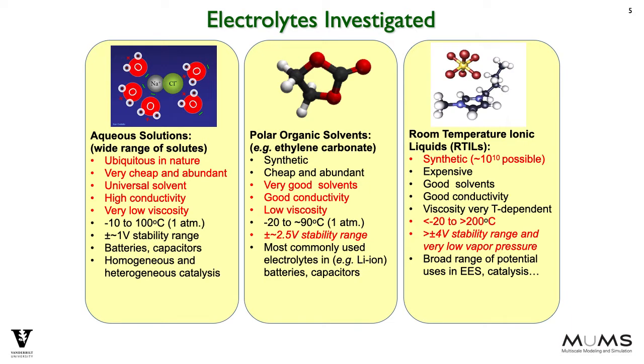The electrolytes we have studied in the FIRST Center include aqueous electrolytes, which have many positive properties, but are limited in electrochemical stability to plus or minus 1 volt due to the water. This leads to replacing water by polar organic solvents, such as ethylene carbonate, which have better electrochemical stability, plus or minus 2.5 volts approximately, but at higher cost. Another approach which has been pursued by many researchers recently is to use neat room temperature ionic liquids so that there is no solvent in the electrolyte. These have high electrochemical stability, approximately plus or minus 4 volts, and wider operating temperatures, but also higher costs and can be highly viscous, thus reducing power density.